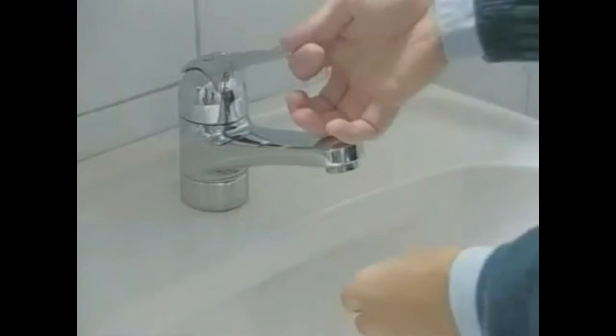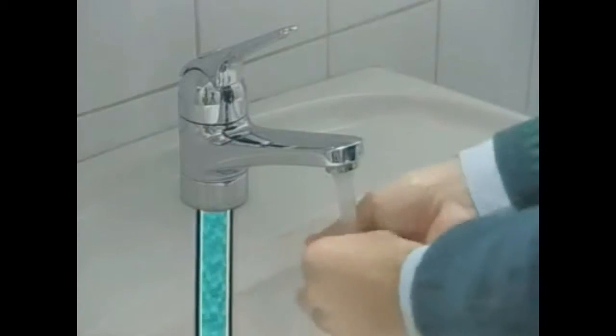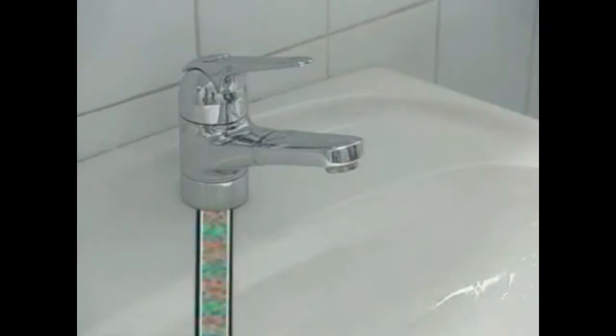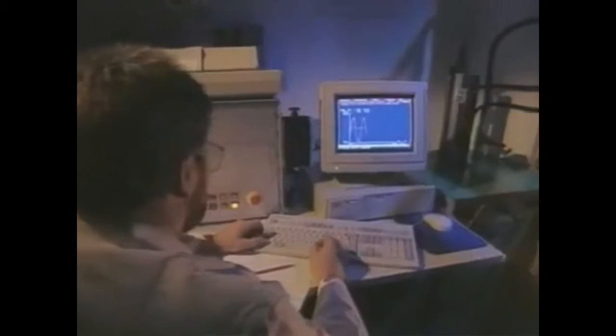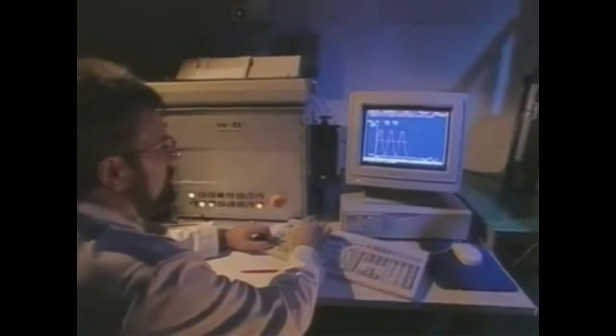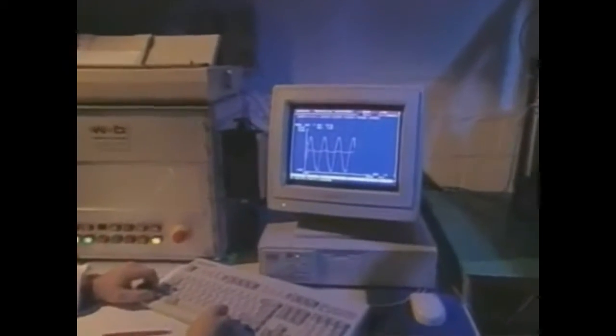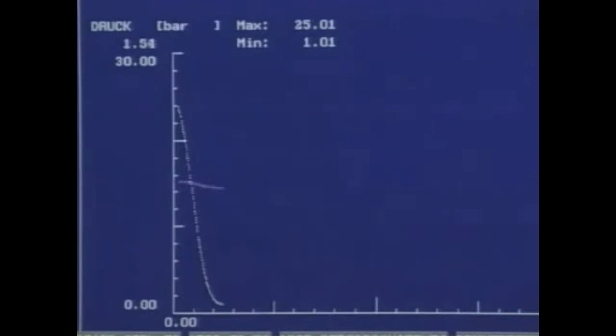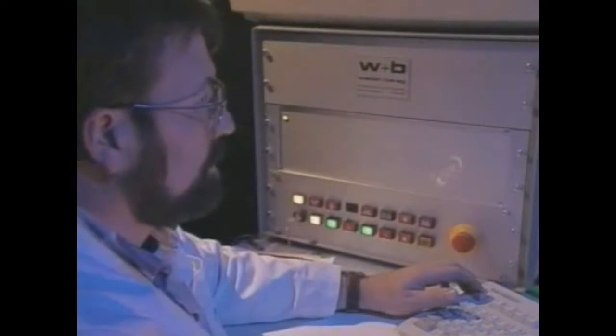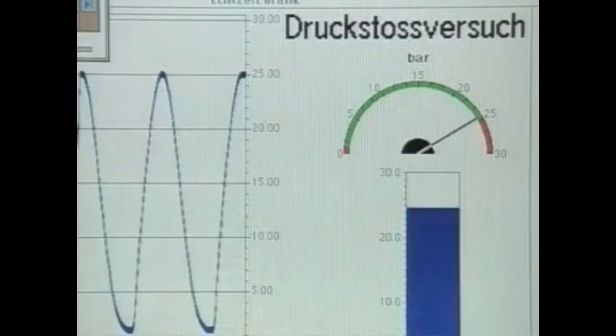In this test, the effect of strong vibrations in the system is checked. The vibrations are several times higher than those expected in normal everyday use. Fittings such as single lever mixers can give rise to strong pressure surges in pipe systems. In the laboratory, the Geberit Mepla system is subjected to pressure surges twice as great as those normally encountered. With 30 pressure cycles per minute, the test samples are exposed to 10,000 pressure surges. The Mepla system passes this test with flying colors.